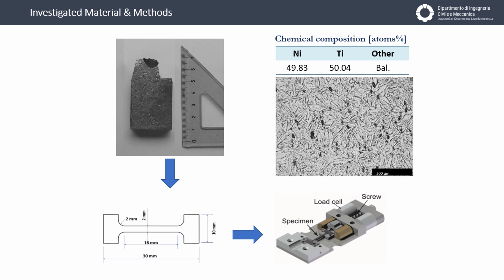Then, starting from the ingot, mini dog bone specimens have been produced like this. You can see that the calibrated length is around 16 millimeters, and the total length of the specimen is 30 millimeters.